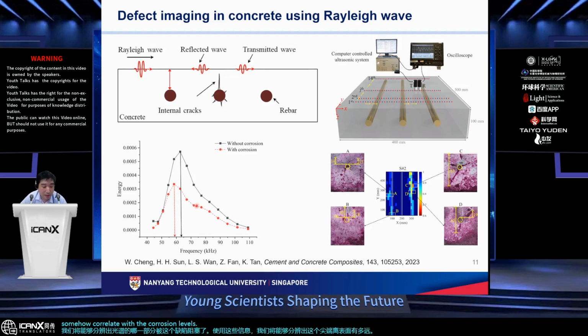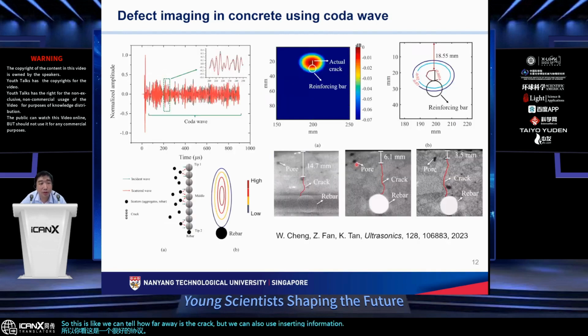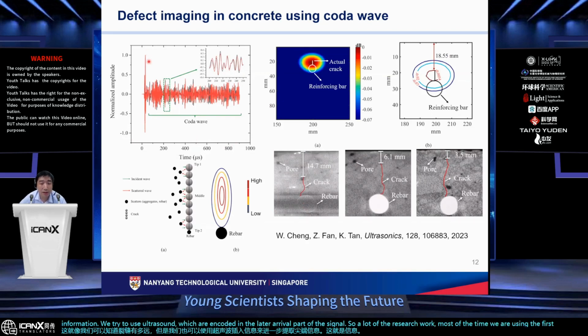Right? So this is some research work we just published last year. We made some corrosion maps from around the rebar, and this is the comparison between these images and those crack images. So this is a pretty good agreement. So we can tell how far away the crack is, but we can also use certain information from ultrasound to extract the tip information further. This is the information encoded in the later arrival part of the signal. In a lot of research work, most of the time we are using the first arrival, which always carries the reflected signal.